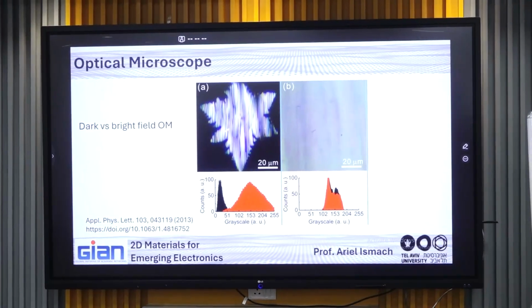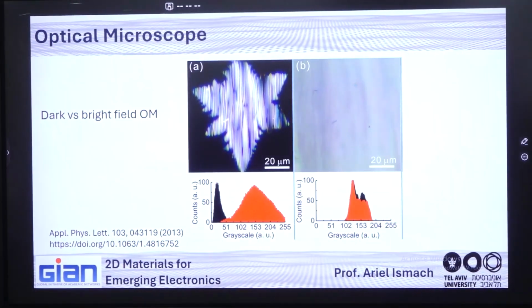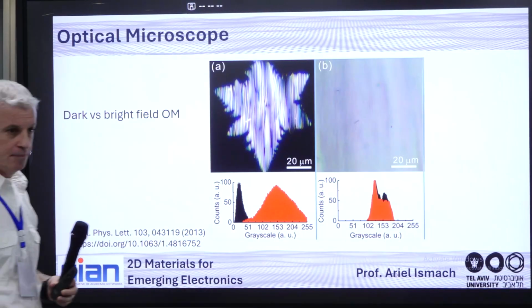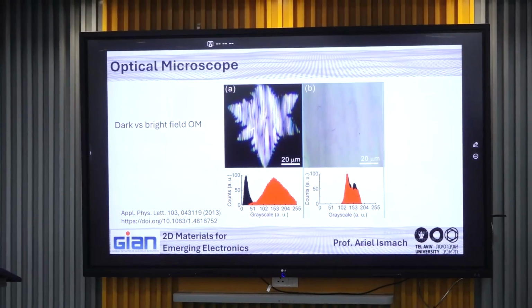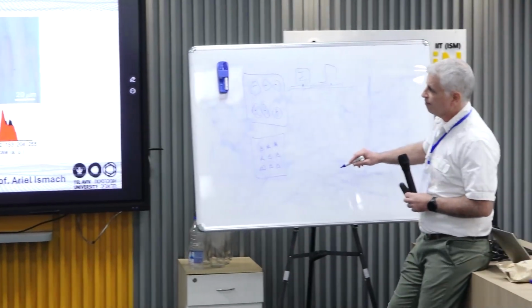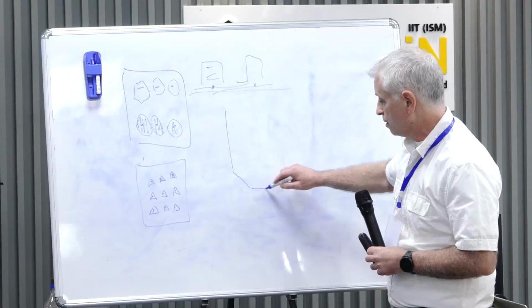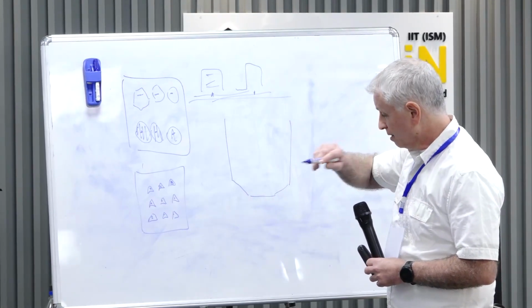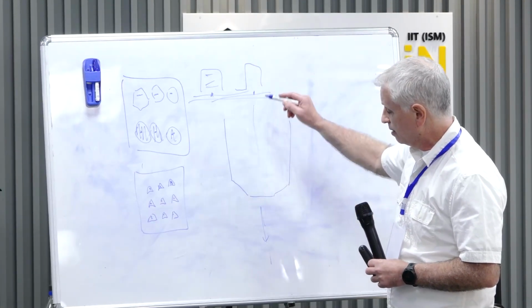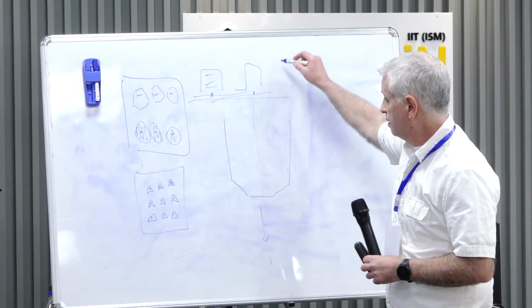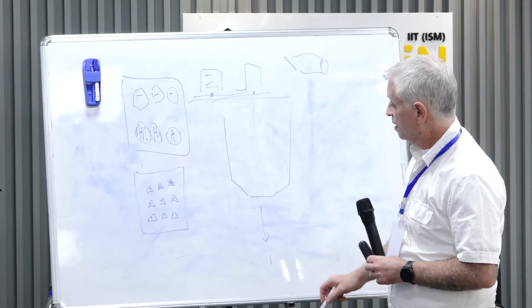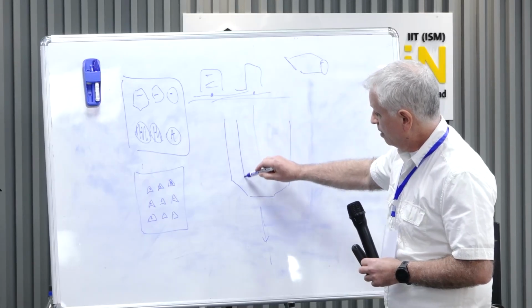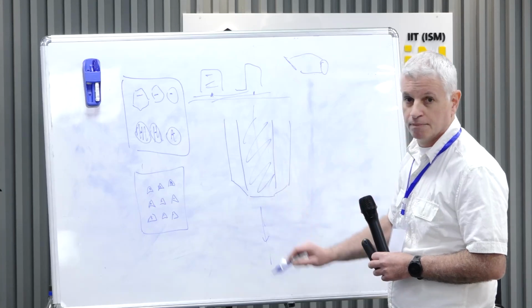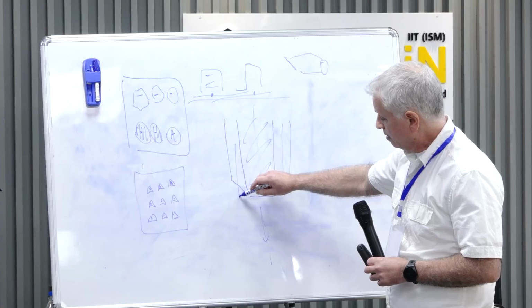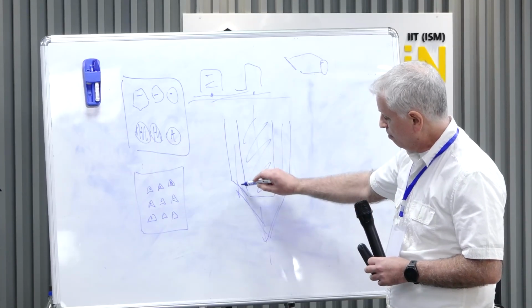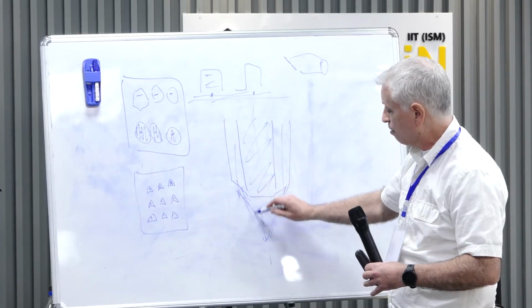Another way also with optical microscope, but in this case with another addition to the optical microscope. Are you familiar with dark field? In order to do dark field with optical microscopy, you need objectives that support that, of course. In bright field, the light comes down and is reflected back to the microscope in order to see it here, through the binoculars. In dark field, the path in the center is blocked, so you have light only at the edges. That light comes to the sample from the side, like making a cone.